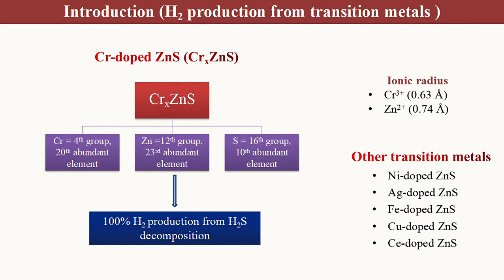To reduce the use of fossil fuels, different transition metals were used for hydrogen production. In our research, we used chromium-doped zinc sulfide photocatalyst. It showed 100% hydrogen sulfide conversion. Due to the close ionic radius of chromium and zinc, it is easy for chromium to substitute zinc and penetrate the host lattice of zinc sulfide. Some other transition metals like nickel-doped zinc sulfide, and silver, iron, and copper-doped zinc sulfide were also used for hydrogen production but did not show the best activity compared to chromium-doped zinc sulfide due to their physical and chemical properties.